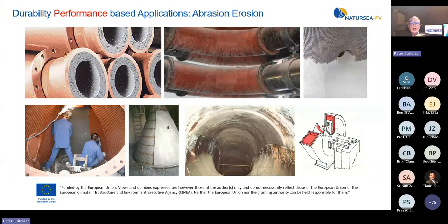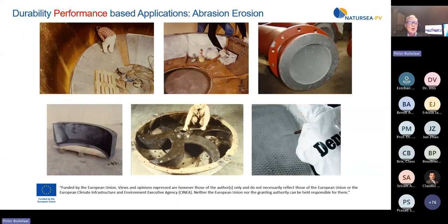For example, wear linings, cyclones, ventilators and transport linings, sometimes in very large diameters, can be lined with UHPC. In some cases, the UHPC is exposed to very high temperatures, up to 1200 degrees, and or aggressive products. UHPC can, like a traditional concrete, be designed and used for several application methods: prefabricated elements, manual application, poured between an inner and outer liner, and sprayed. Often UHPC could replace other materials in machine parts, like cast iron in the screw feeder for the cement industry.